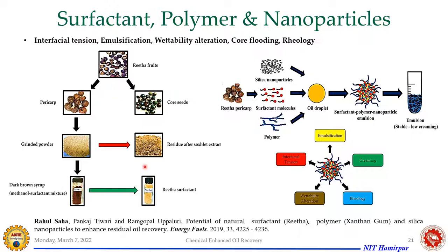So we take the surfactant, and we blend it into this polymer, because heavy crude oil IFT needs to be reduced to a very low range. So we took this Reetha surfactant, nanoparticles, and the polymer, we blended them, and we tried to see different properties, and how much oil is collected in the effluent, so that we can have a higher percentage of residual oil recovery. So this interaction is being studied.